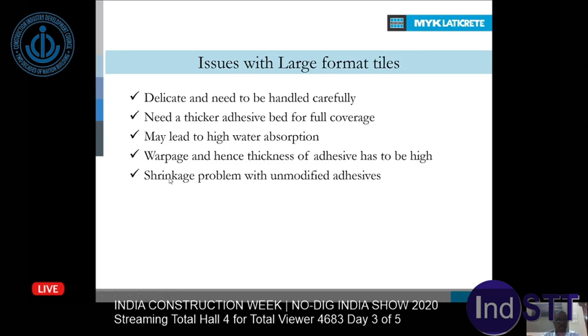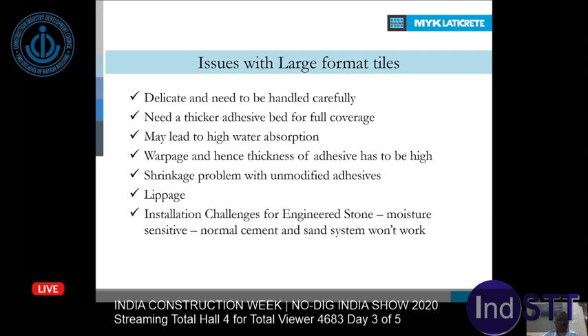The moment shrinkage happens, tiles start taking the stress and cracking, and that especially comes with the unmodified adhesives or the cement and sand slurry. And also, when you go to the large format, lippage is a very common problem. That means you will see undulations. When your floor is done, you can see the ups and downs on the grout joints.